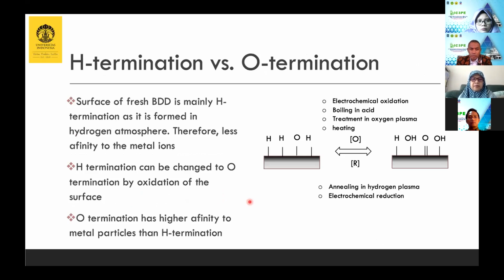Next, diamond is synthesized in a hydrogen atmosphere, so generally it has a hydrogen terminated surface, and this is not good for attracting metal particles. If we can oxidize it to be oxygen terminated, it will be better, because oxygen and metal have some positive-negative interaction, so the attraction will be better.